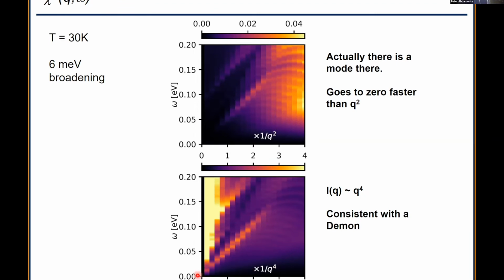So what you can see is that there is a gapless mode in strontium ruthenate in RPA, and it seems to be a demon in the sense that it doesn't satisfy the F sum rule by itself. It goes faster than that, which would mean if this excitation were the only thing in the problem, if you calculated epsilon, it would be 1, because it wouldn't be able to screen, at least in the long wavelength limit.